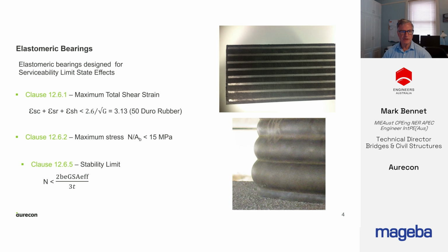Elastomeric bearings are designed for serviceability limit states. This photo shows a cross-section of a laminated elastomeric bearing. What you're looking for is nice uniform layers of rubber with parallel steel plates. In this bearing, the side cover is a bit deficient and the corners of the steel plates should be rounded. Failure modes include splitting of elastomer and delamination of the elastomer from the steel plates.